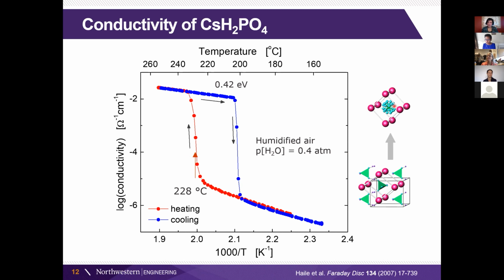And the phosphate group, which was sitting here in a specific orientation, undergoes a rapid reorientation. It's a tetrahedral unit that's sitting in an octahedral site of octahedral symmetry, and so it's got 6 different orientations. And as it reorients here, it moves the proton from one oxygen to the next. And every once in a while, the proton can transfer to the next phosphate group in the neighboring unit cell.